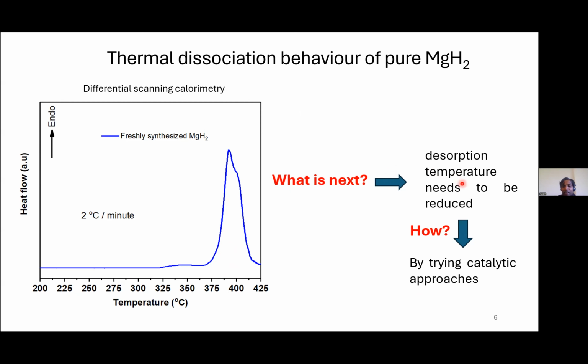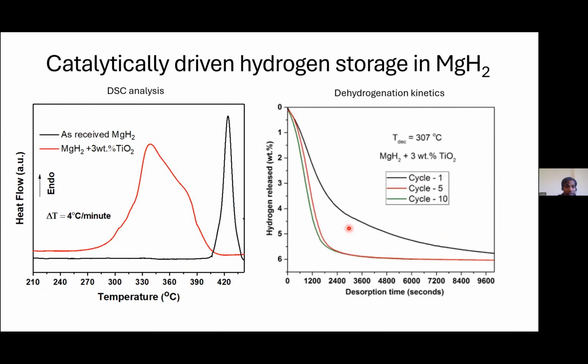The next is, we need to reduce the dehydrogenation temperature of the system if we ever need to imagine utilizing this material for vehicular applications. Then how do we do it? By catalytic approaches. We need to find the appropriate catalyst that can reduce the dehydrogenation temperature of the system. And several catalysts are there. I will tell one example. We have utilized titanium dioxide, and that is why, as a multifunctional material, I took the example of titanium dioxide in the first slide itself. It's a very, very good material for various applications.